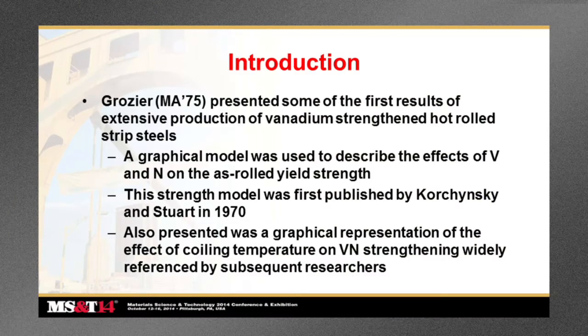Grozier in 1975, Microalloying 75, the symposium that really started microalloying, which Mike Korchynsky was a very prominent contributor to. In that conference, Grozier presented some of the first results of extensive production of vanadium strengthened hot rolled strip steels. In there, a graphical model was used to describe the effects of vanadium and nitrogen on the as-rolled yield strength. This strength model was first published by Korchynsky and Stuart in 1970. Also presented in that conference was a graphical representation of the effect of coiling temperature on vanadium nitrogen strengthening, which has been widely referenced by subsequent researchers over the years.